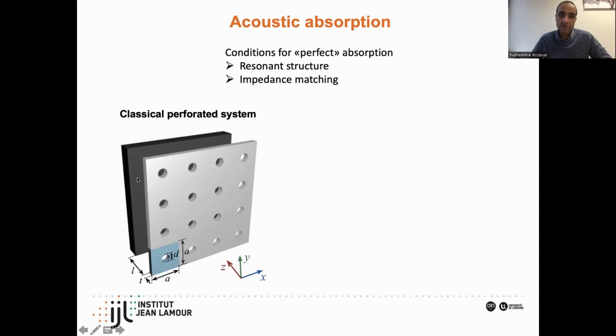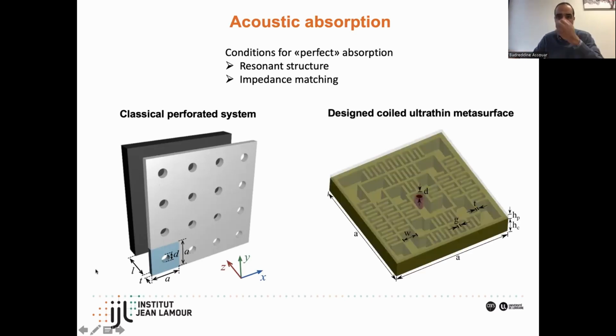And typically, the resonance is related to the thickness of this air cavity, which means that if you would like to use this concept to absorb a frequency of about 100 or 200 hertz, you need a thickness of about 2 or 3 meters, which is not practical. So that's why we developed this kind of coiled ultra-thin metasurface, another work based on the very first one, with a labyrinthine channel in order to go toward low frequencies.